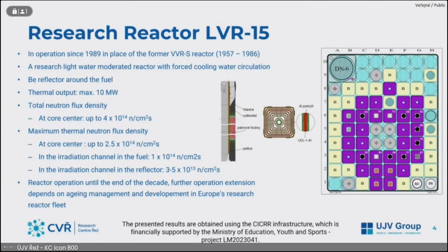However, the calculation is one side of the problem. When it comes to the practical data from the reactor operation, we are still finding some gaps between the calculation and the measured data, and there are still some approximations used in our models, and the methods that we use need to be qualified on precise measured data. Here on this slide, you can see the active core of the LVR-15 reactor.